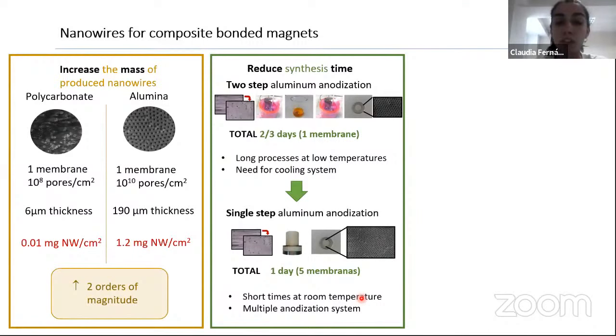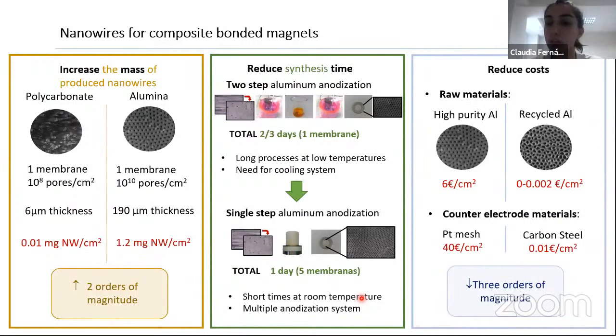So we modified some parameters of a common 2-step aluminum anodization, and we reached the production of 5 templates per day. And in order to reduce the costs, we changed the raw materials. We changed high purity aluminum for recycled aluminum, and also we changed the material of the counter electrode in all the electrochemical processes. And with that, we decreased by 3 orders of magnitude the cost of the production of the nanowires.